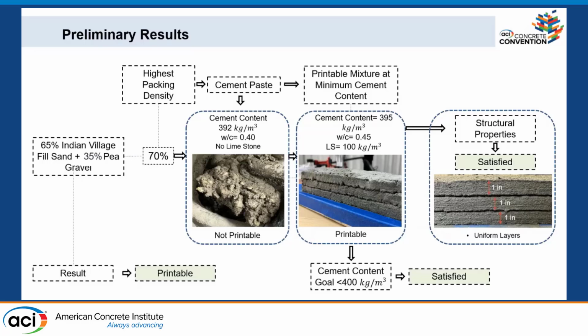For the next part, we have tried 65% Indian village fill sand and 35% pea gravel, and we got the packing density of like 70%. Here, the cement content that we got was like 392 kg per cubic meter, and with no limestone, it was not printable as well. To make it printable, we used some limestone and increased the water content ratio, and you can see the results here. We got uniform layers with the printing, and it satisfied the shape stability. Also, it satisfied our cement content goal that was below 400, which is 395 kg per cubic meter, and the result is printable.